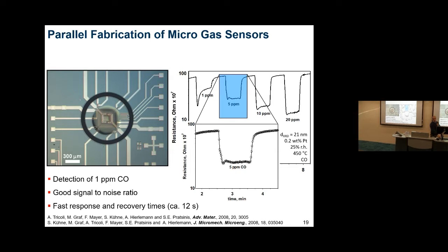The reason why it works very well is, again, the structure. What we have here is a hierarchical structure of nanoparticles, very porous and open. This was an example to show you that if you're able to control the structure of this material, then you're also able to control the performance of the device, a very small device.